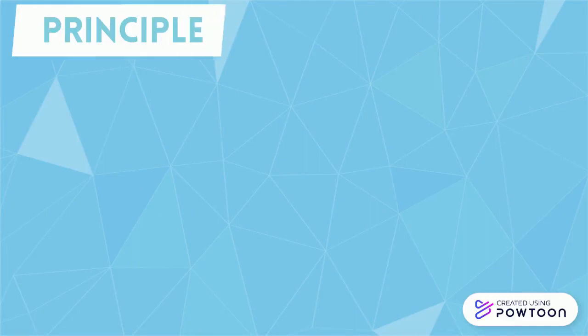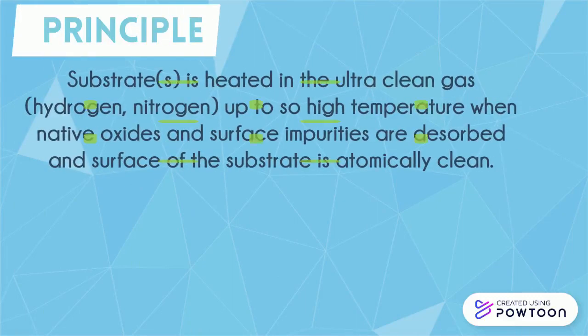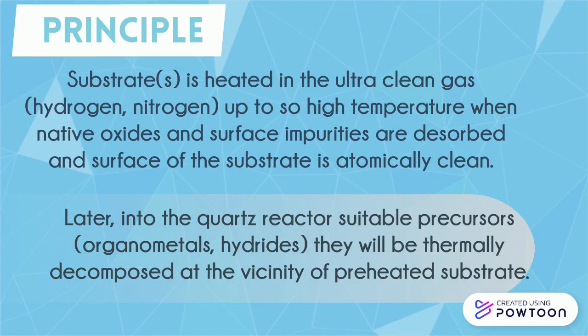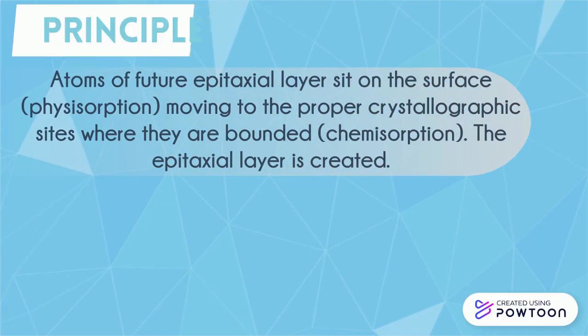The principle: the substrate is heated in an ultraclean gas, for example hydrogen-nitrogen, up to a high temperature where native oxides and surface contaminants are desorbed and the substrate surface becomes atomically clean. Inside the quartz reactor, precursors are thermally decomposed onto the preheated substrate. Atoms of the future epitaxial layer sit on the surface via adsorption, moving to favorable crystallographic sites where they are bonded, and the epitaxial layer is created.